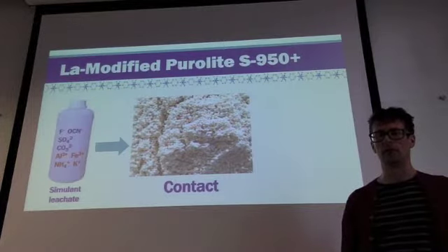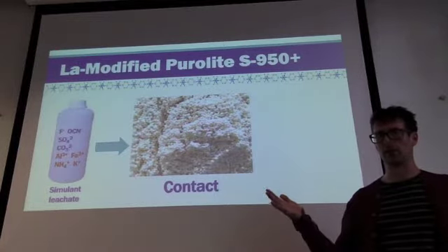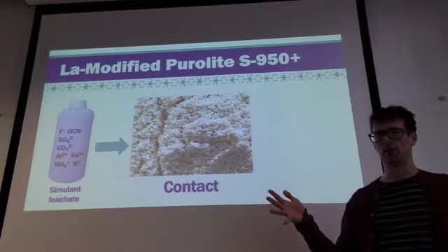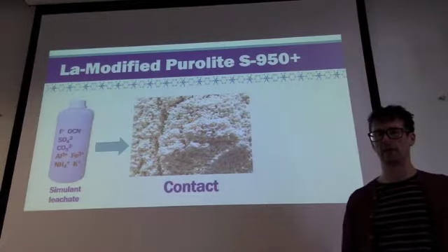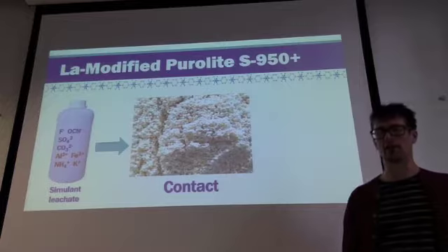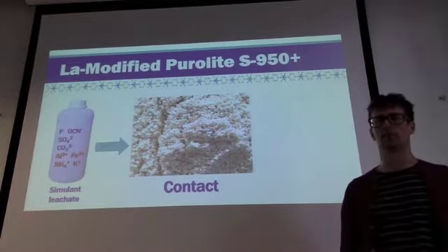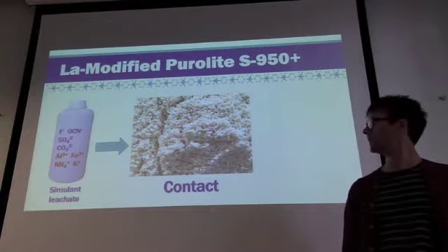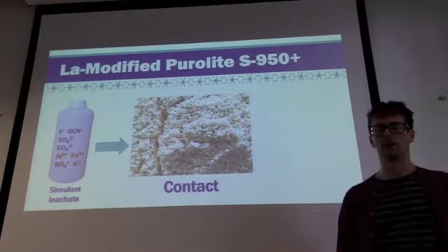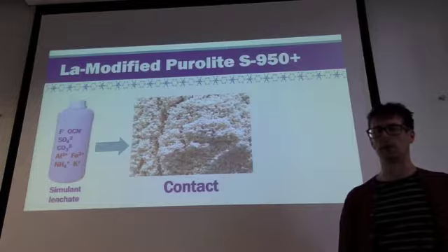So we have an aqueous solution of known fluoride concentration, but importantly to this we've also added some of the other common cations and anions that we believe through literature studies would be solubilized through the alkaline leaching of SPL. So as well as fluoride we have sulfate, carbonate, aluminium notably, and also iron, ammonium and potassium.